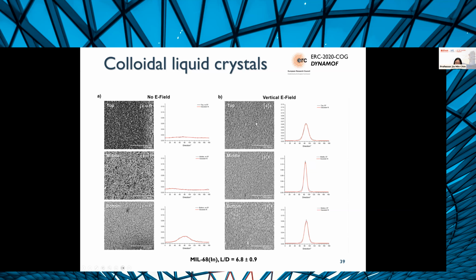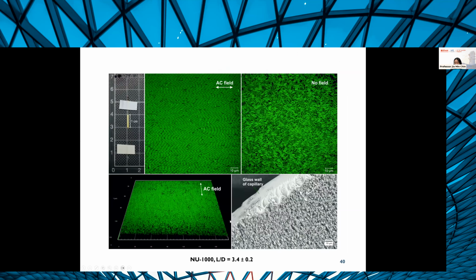Now, if you apply an electric field instead and you pack them, you see that regardless of where you are in the capillary, once again, you get very beautiful orientation. And then we moved on to particles of much lower aspect ratio, 3.4 in this case. This was exciting because this was lower than the minimum that we require in the absence of an E field. And we found that indeed these particles actually align very, very beautifully.